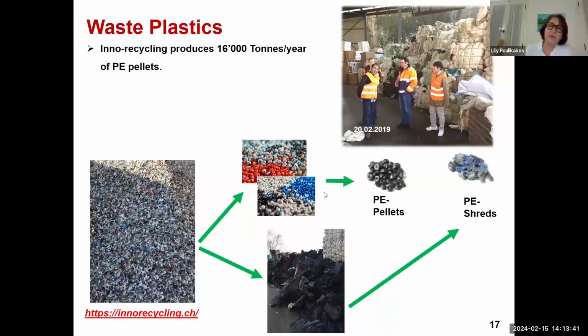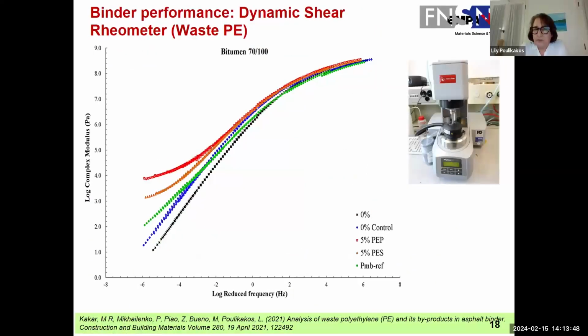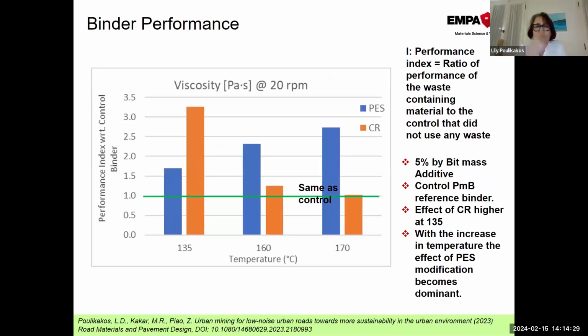So we picked up both of these plastic wastes and brought them into our lab, added them to our 70/100 straight run bitumen, and looked at it with our DSR. What we saw is that both of the plastics, the red and the orange plot, show an increase in the modulus at the high temperature zone, even more than our reference that was polymer modified, shown here in green. So we thought that there's a potential for these waste plastics to help in the high temperature range, for example, for rutting. However, I will show you the mixture results in a few minutes.